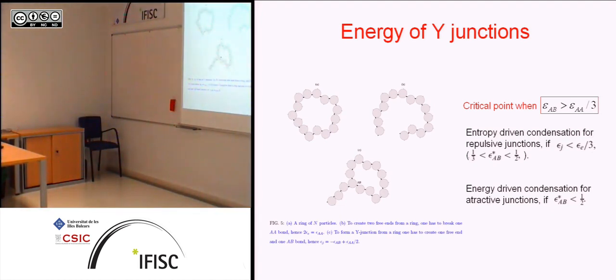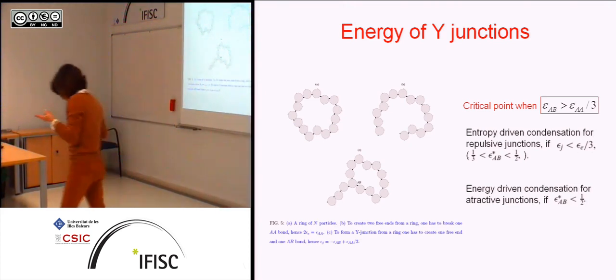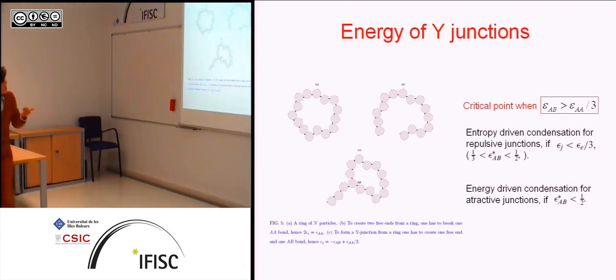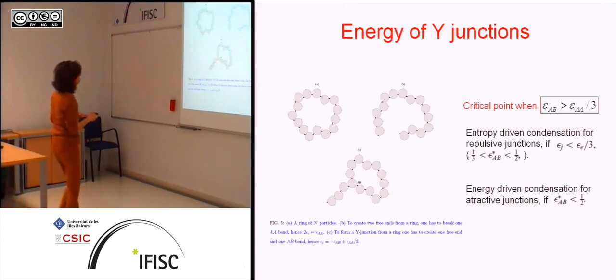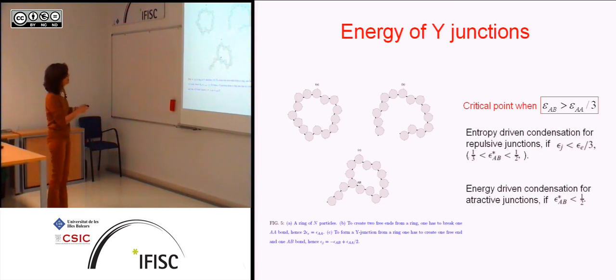And we can distinguish two types of junctions, attractive and repulsive junctions. And this is the critical point that we found, which occurs only if this interaction is greater than the main chain interaction divided by 3. And we find two types of condensation. There are two surprises. First of all, one is the AB interaction. The other is the interaction of this junction. To make this junction, we have to break the ring and put an AB there.